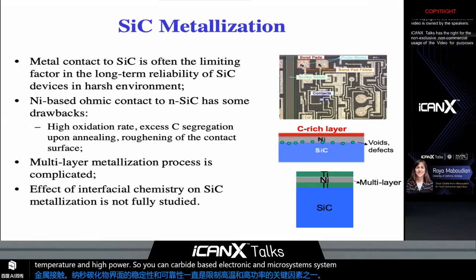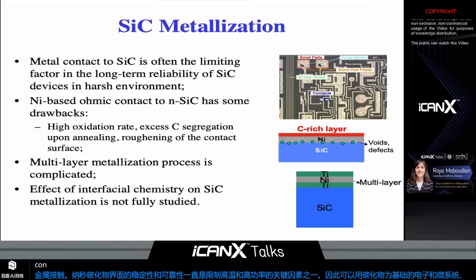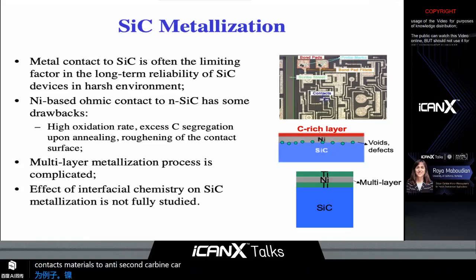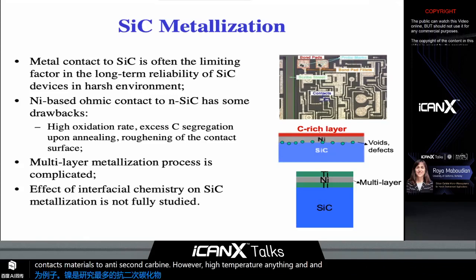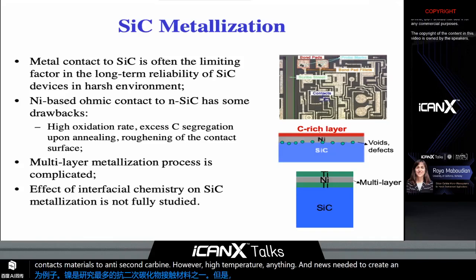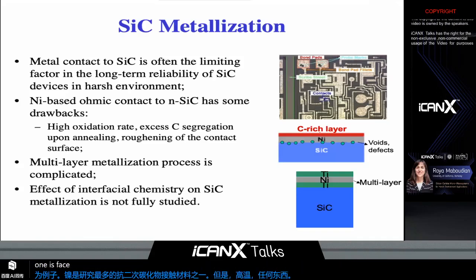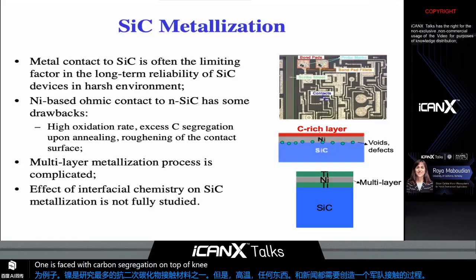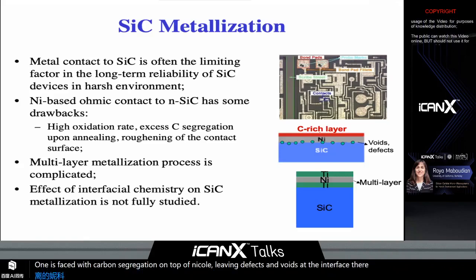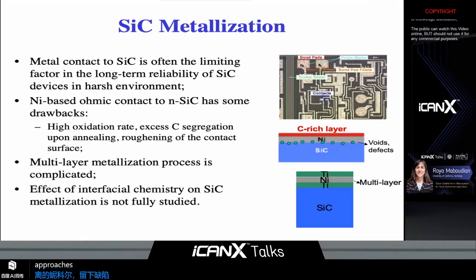As an example, nickel is one of the most studied contact materials to N-type silicon carbide. However, high temperature annealing is needed to create an ohmic contact. But in the process, one is faced with carbon segregation on top of nickel, leaving defects and voids at the interface. There have been many approaches to develop more robust metallization schemes.